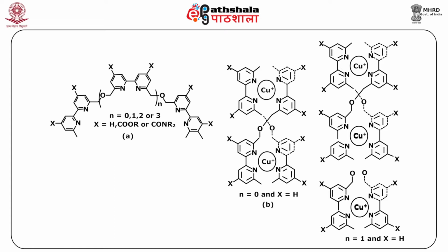It results from the tetrahedral-like coordination imposed by each copper bipyridyl + complex site from the design of the ligands, which disfavors binding to only a single strand. In such instances, double helix formation requires self-recognition by the two helicands, and that leads to preferential formation of the double helical structures. I hope this example and this figure clearly justify self-assembly in the case of inorganic architectures.